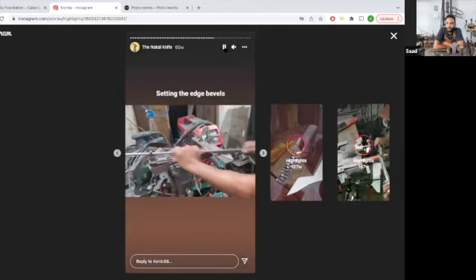So now you're putting in the final edge bevels. You can't grind the edge in earlier, because when you're doing the heat treating process, if the edge is too thin, because of the high temperature it starts to melt or deform. So you don't put an edge in until the tempering is done. You finish your heat treat processes and then you come in and start putting an edge.